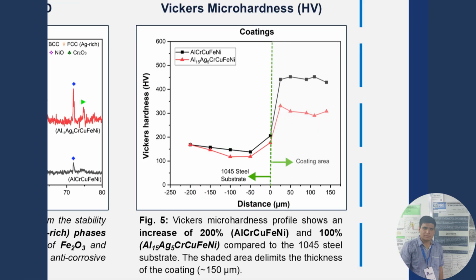In terms of mechanical performance, the Vickers micro-hardness profiles demonstrate a massive improvement over the untreated steel substrates. The baseline aluminum, chromium, copper, iron, nickel coating increased the surface hardness of the 1045 steel by an outstanding 200%, while the silver-containing coating showed a 100% increase. The shaded area in Figure 5 delimits a uniform coating thickness of approximately 150 micrometers.